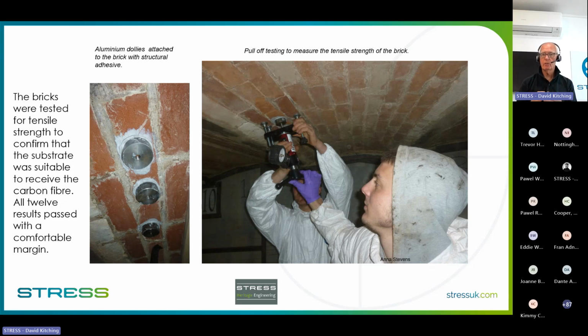Now, what you really want to see, ideally, is the adhesive pulling part of that brick surface off, or if you're doing it to concrete, part of the concrete, and then you know exactly what that bond strength is going to be. And what we're looking for is a figure of 1.25 newtons per millimeter squared as a bond strength. If you achieve that, then you're going to fully maximize the potential of the carbon fiber.